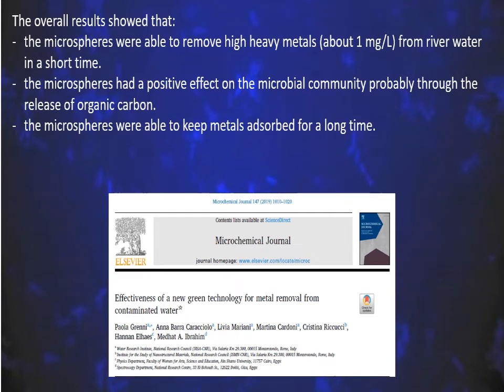The overall results show that the microspheres were able to remove high heavy metals, about 1 mg per liter, from river water in a short time, and the microspheres had a positive effect on the natural microbial community of the river water, probably through the release of organic carbon. The microspheres were able to keep metals adsorbed for a long time.